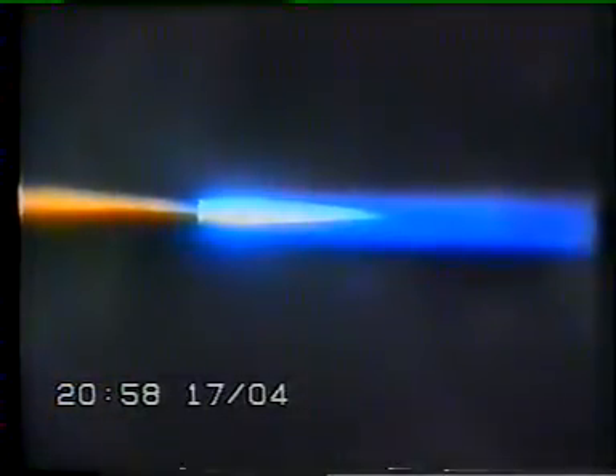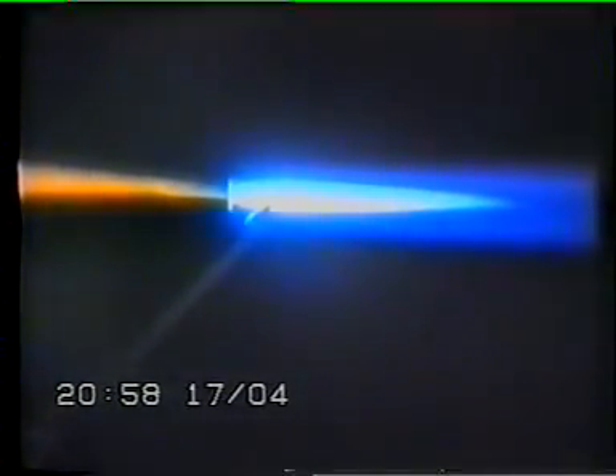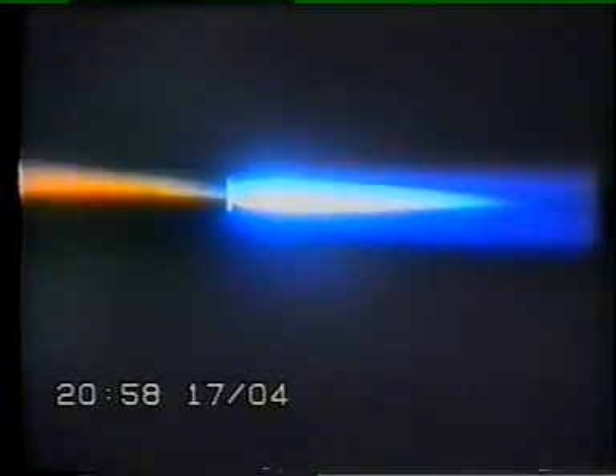This correct flame has 3 parts. The largest part is the envelope. The envelope contains the feather and the cone. When the feather and cone coincide, the flame is called neutral. Adjust the valves until you get a full outer flame and a sharp pale blue inner cone. The tip of this inner cone is the point of the highest temperature.